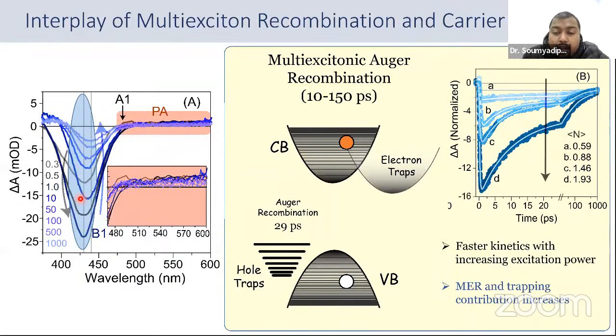And how do we know that? We did a fluence dependence study of that. With the increase in pump fluence, the kinetics is getting faster. Now here you can see delta N. Delta N is basically the average number of excitons produced due to the pump in that system. As you can see, when you increase the average number of excitons, you are getting faster kinetics, which basically shows multi-exciton relaxation and trapping contributions as well.